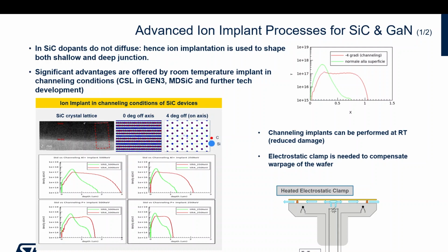In the case of silicon carbide, the entire shape of the dopant pocket is determined by where the ions are put by ion implantation itself. So if you want to make a 1 micron thick p-type layer, for example, you need to make several implants because you cannot diffuse. So you have to put the dopant up to 1 micron. So in silicon carbide, what is called implant in channeling condition is getting more and more important.